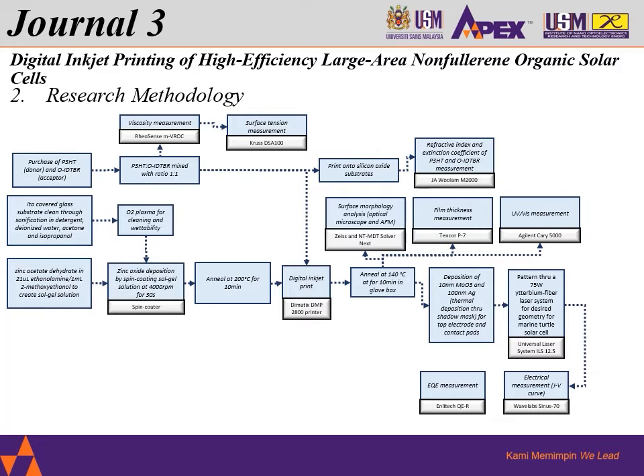Before going to the final digital inkjet printing event, this ink mixture was first printed on a silicon oxide substrate. This was done to find out the refractive index and the extinction coefficient of the P3HT and O-IDTBR, the acceptor and the donor itself. And then only we go for the digital inkjet printing with a set of parameters. After it is printed, this will be annealed at 140 degrees Celsius.